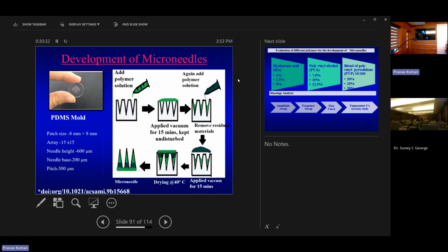Then vacuum can be applied, or we can do centrifugation so that it goes into this. Then we can keep it undisturbed for some time. Then whatever residue is there, you can remove it. Then we can add material again. If you want, you can add drug. Then again applying vacuum. Then drying at 40 degrees Celsius. This temperature will depend on our choice of polymers. Depending on our polymer, we have to choose this drying condition. Then after a particular time of drying, you can just tap it, and the microneedle will come out of it. It will be a flexible material.